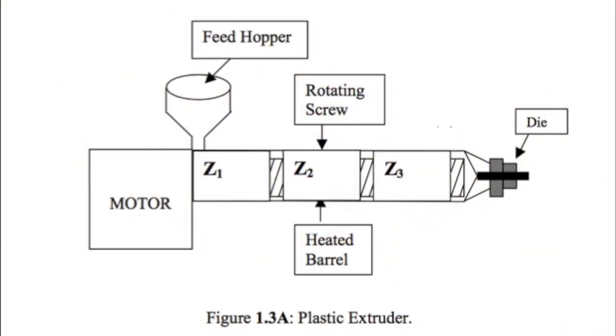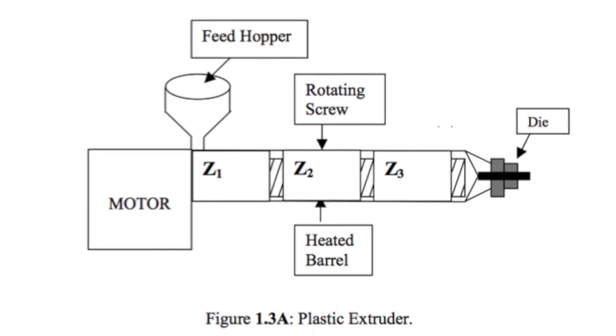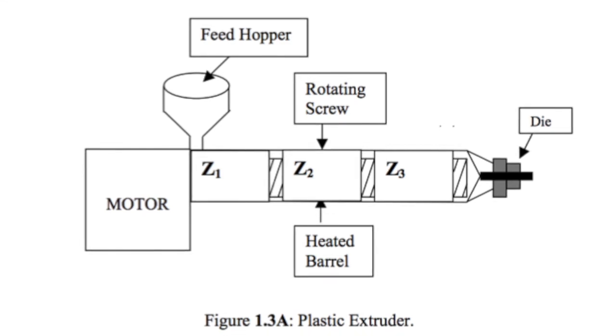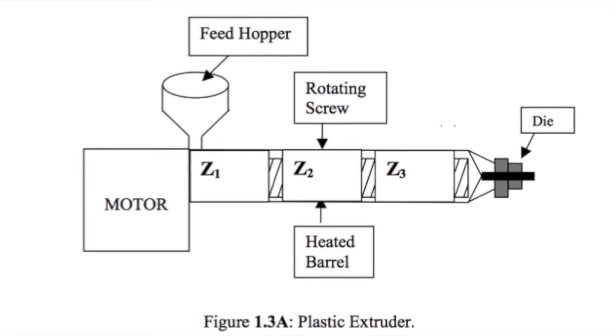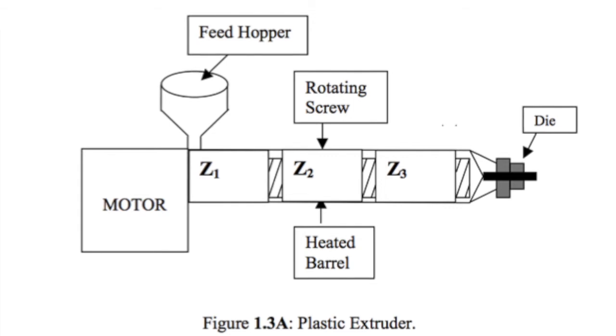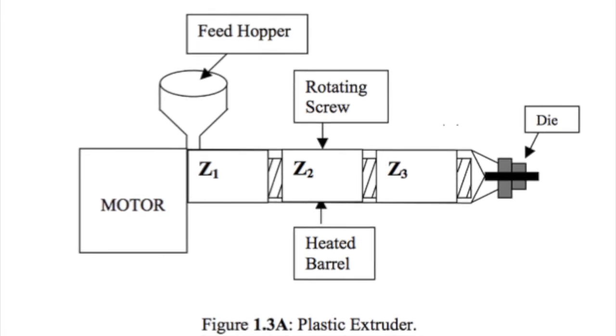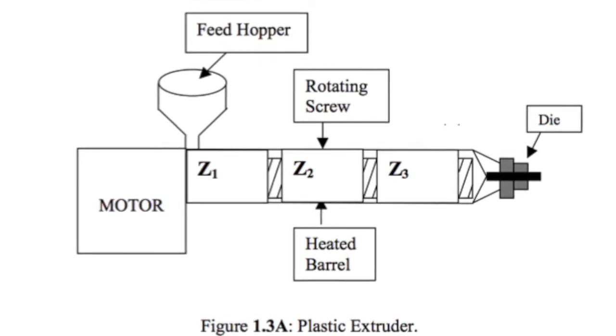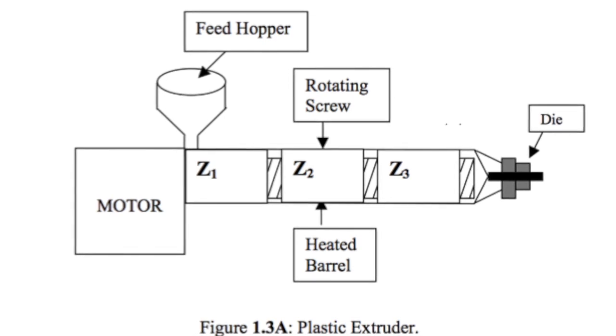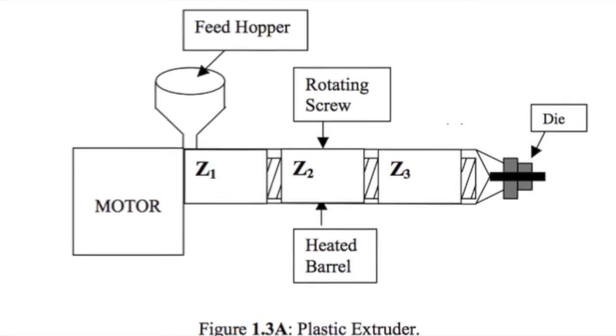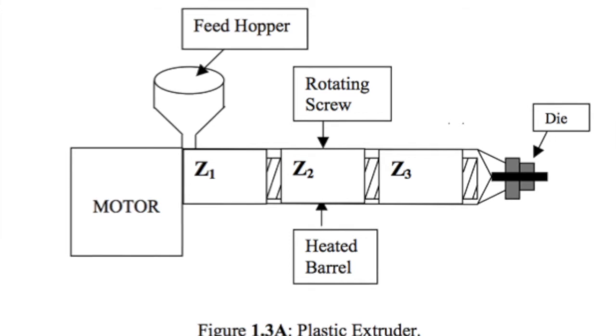There are 3 methods for the processing of PHB polymer that is extracted. Firstly, there is the plastic extruder. This process produces the polymer in pellet form, which is further used to produce films, bottles, and injection molded parts. The task of the extruder is to take the solid plastic and using heat, pressure, and shear to transform it into a uniform melt which can then be delivered to the next processing stage. The final melt must be uniform in both concentration and temperature.